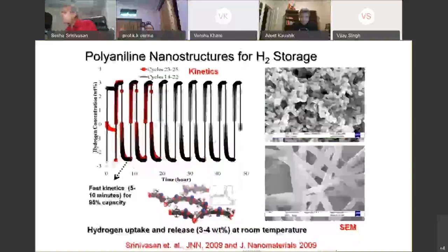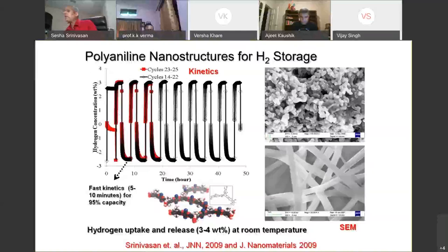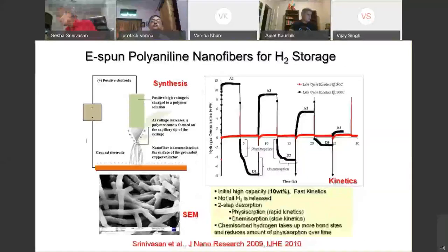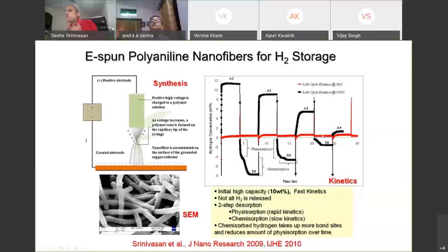Then the soft material we looked into is called polymer nanostructures, polyaniline nanospheres and nanofibers. We tried to prepare nanospheres using a template-less and template process with a chemical route, and looking at hydrogen storage on these porous nanostructures, we were able to get up to 3% hydrogen at room temperature. That's unheard of. We got the cycling capacity, we improved the storage capacity, but there is an intrinsic problem about the reversibility. Sometimes if we go for nanofibers by electrospinning, then we also see up to 10% hydrogen uptake, but over time the capacity goes down. So we are developing the PANI or polyaniline nanofibers even now for electrochromic and thermochromic applications.